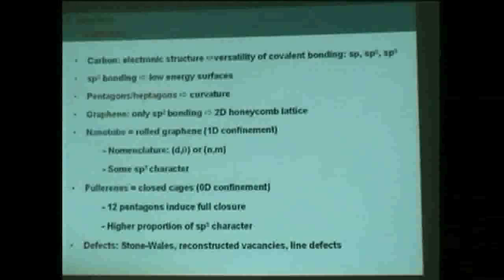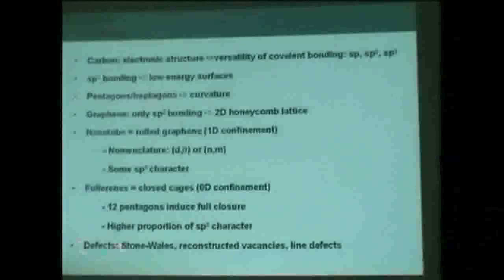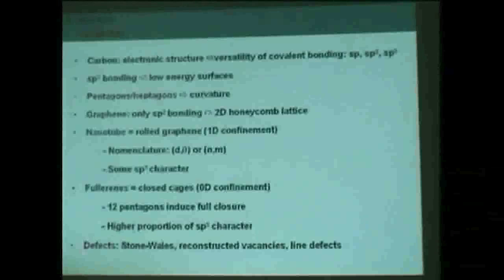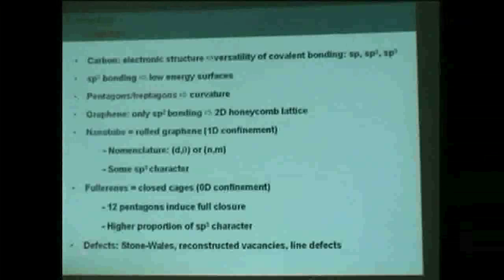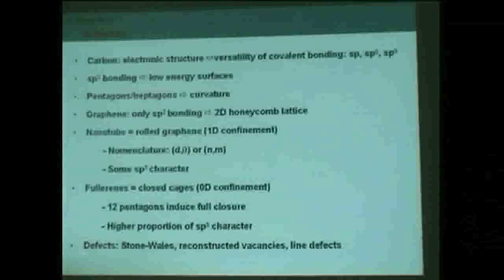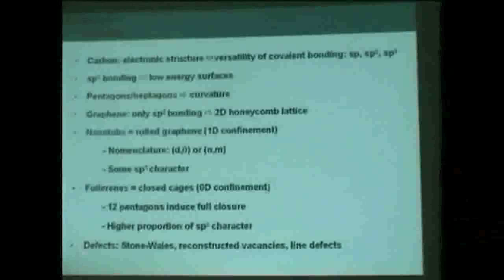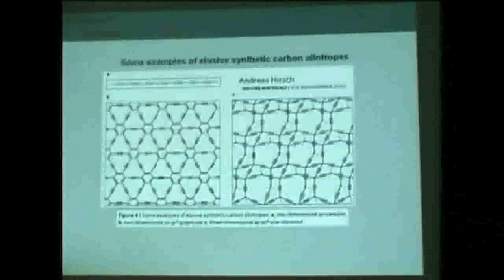Fullerenes, which are fully closed, which are not crystals, have no translational symmetry. And of course, in all those materials, you can have defects, and those are important for the properties, depending on the amount of defects. The mechanical properties, the electronic properties will be very different. And you, as a materials scientist and scientist, you have to take that into account.